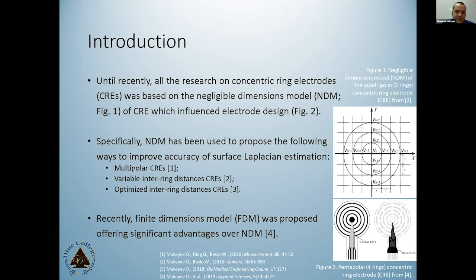We first studied the impact of increasing the number of rings, because this started with a bipolar electrode, a single ring and the central disk, tripolar electrode, 2 rings and the central disk, etc. So we increased the number of poles, the number of rings further to 3, 4, 5, 6, 7. Showed that we can increase the Laplacian accuracy with each additional ring, because in that Taylor series expansion, we can cancel out an additional truncation term with each additional ring, and canceling out the additional truncation term translates into decreasing the truncation error, which in this case is the error of Laplacian estimation.